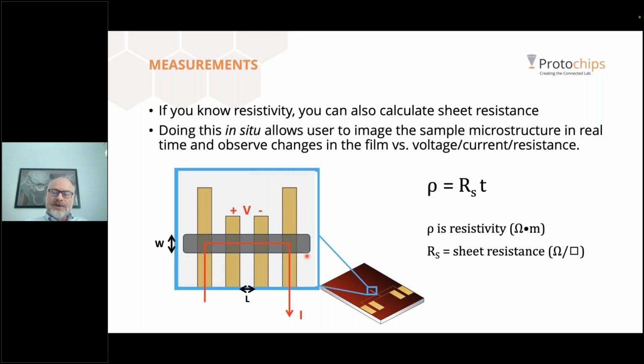Going one step further, you can also calculate the sheet resistance in this way. So sheet resistance is really useful to circuit designers because it determines how long and wide conductors need to be, for example, to supply a certain amount of current. It also shows, for example, you can decrease sheet resistance by increasing thickness. You can see the trade-off here for a material that has a given resistivity. So for long runs of metal on a chip and some of the higher metal levels, you may need to go thicker to minimize resistance. Equations like this help you calculate what you need. So the sheet resistance feeds the models that circuit designers use. It also drives materials development. Like in some of the cross sections I showed earlier, used copper interconnect, right? So copper interconnect was introduced back in the 90s because aluminum was too resistive and was too prone to electromigration, right?